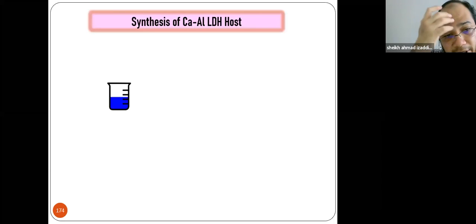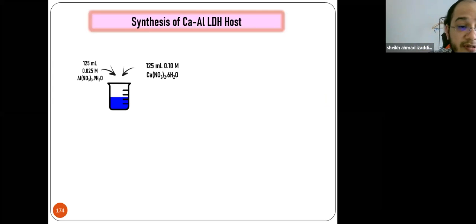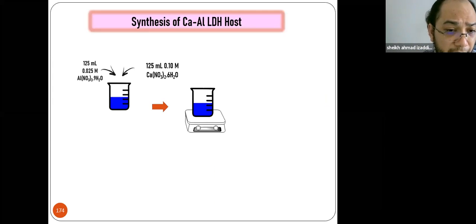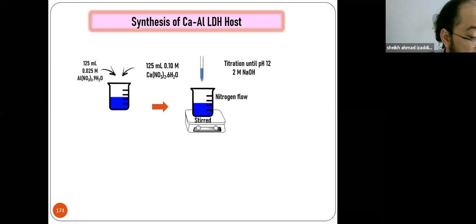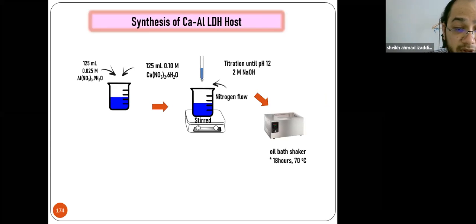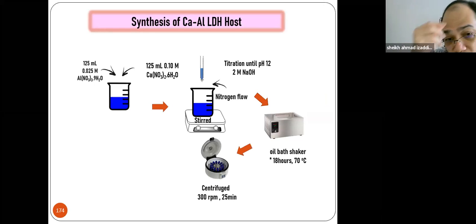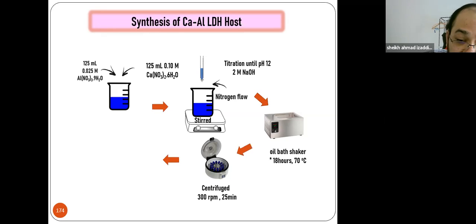So to synthesize the calcium aluminum host, we will mix the aluminum nitrate monohydrate with calcium nitrate hexahydrate. We stir it using nitrogen flow. Why nitrogen flow? Because we want to avoid carbonate or carbon dioxide that will interrupt our result. And then, to get pH 12, we will titrate it with 2 molar sodium hydroxide, put it into the oil bath shaker for 18 hours at 70 degrees Celsius. We centrifuge it for about 25 minutes, 3 times, and then we wash it with deionized water, and then put it into the oven.